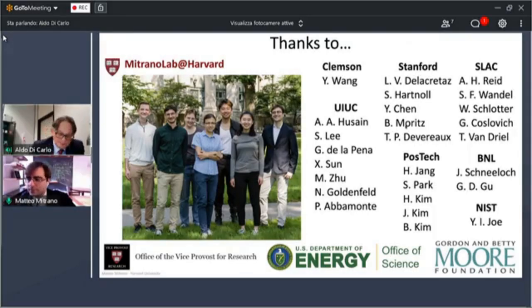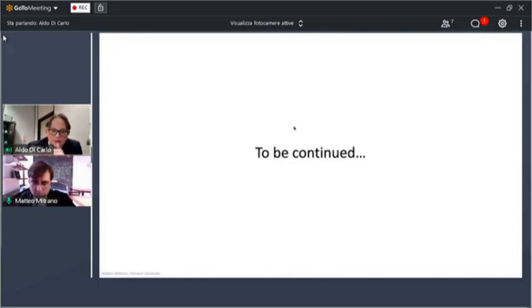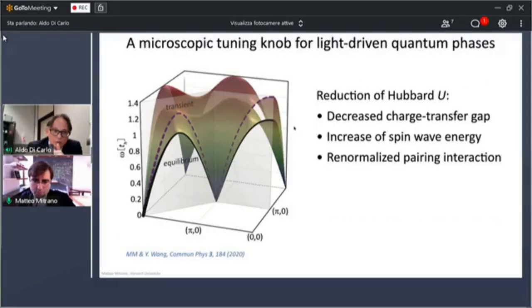Thanks, Matteo. Is there any suggestion about what kind of structure could show this light-induced superconductivity? As far as I remember, you showed that if you go below TC, you suppress the effect a bit, and if you are above, you get the effect. So is there any prescription of a material that maybe could not have a clear TC, but could have light-induced superconductivity? There has been a number of developments in the last few years since my original work.